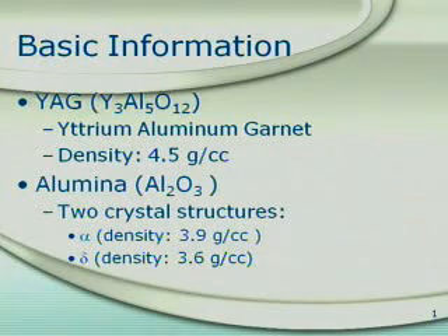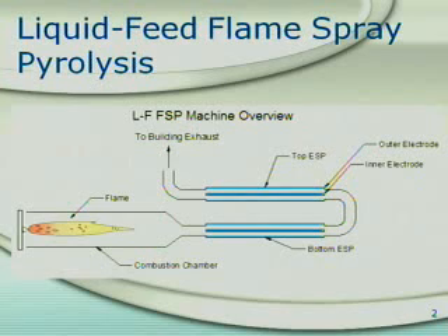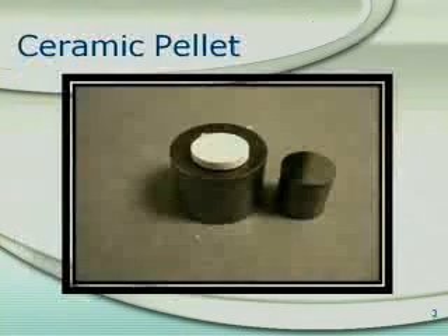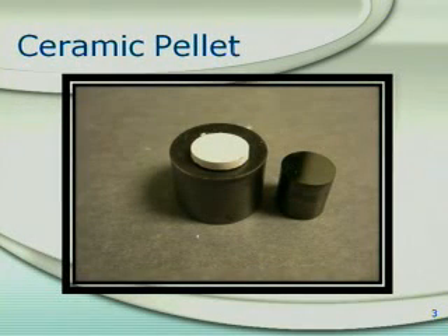Here's a diagram of this process, which begins with organometallic precursors that are aerosolized and burned, then quickly quenched to create nano-sized particles. The powders are suspended in a solvent along with binders and dispersed and then sieved to reduce particle agglomeration. Then they are uniaxially pressed into cylindrical pellets as shown. Each pellet is a small sample used for testing of the powders and processes.